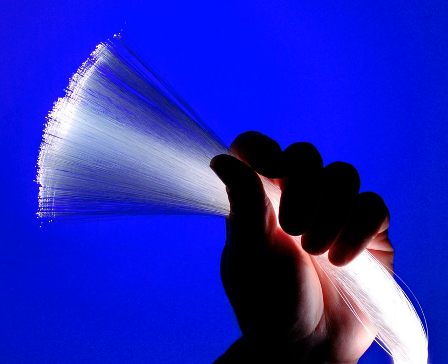Unevenly coated fiber will experience non-uniform forces when the coating expands or contracts, and is susceptible to greater signal attenuation. Under proper drawing and coating processes, the coatings are concentric around the fiber, continuous over the length of the application and have constant thickness. Fiber-optic coatings protect the glass fibers from scratches that could lead to strength degradation. The combination of moisture and scratches accelerates the aging and deterioration of fiber strength. When fiber is subjected to low stresses over a long period, fiber fatigue can occur. Over time or in extreme conditions, these factors combine to cause microscopic flaws in the glass fiber to propagate, which can ultimately result in fiber failure. Three key characteristics of fiber-optic waveguides can be affected by environmental conditions: strength, attenuation and resistance to losses caused by micro-bending. External optical fiber cable jackets and buffer tubes protect glass optical fiber from environmental conditions that can affect the fiber's performance and long-term durability. On the inside, coatings ensure the reliability of the signal being carried and help minimize attenuation due to micro-bending.